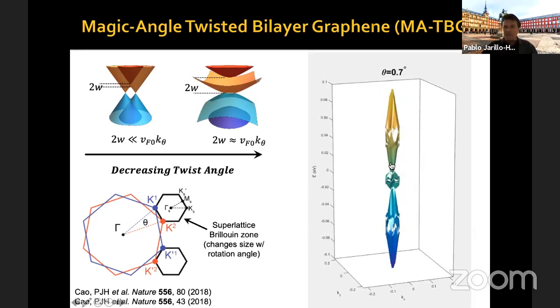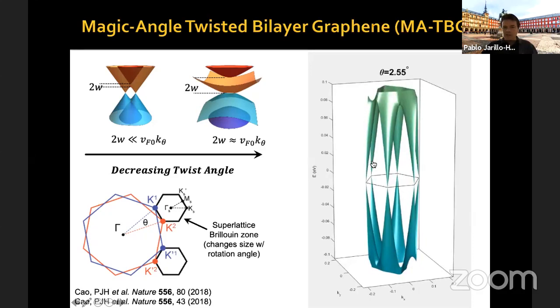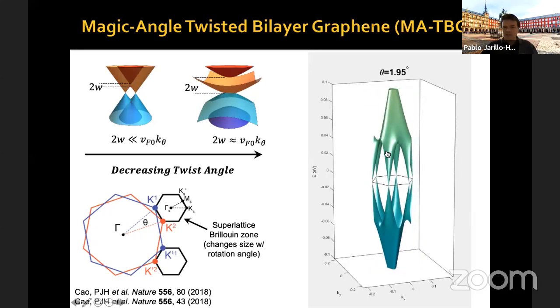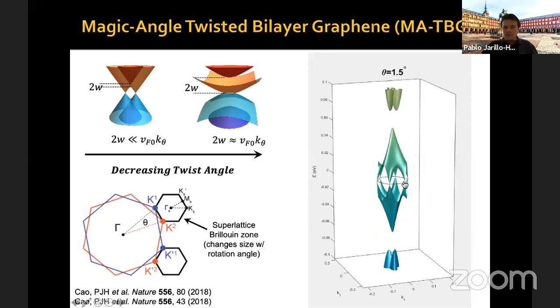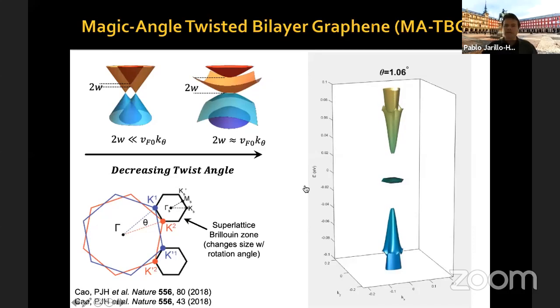And then the band structure continues evolving. Let me run this video again. Okay? You see that this band structure is becoming flatter and flatter. And at about 1.1 degrees, it becomes very flat down there.